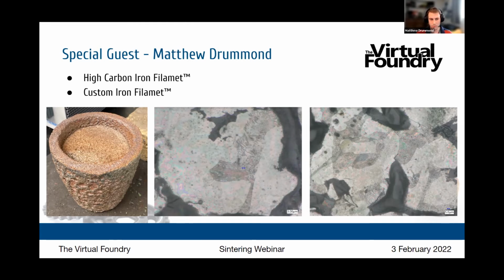I noticed with the crucible before on my sintering process, that actually one side of the crucible had not all the carbon eaten away, and one side was like that beige you see there. And that's because part of the crucible was right under the coil. So one side of the crucible is getting very hot just right underneath the coil, and the other side of the crucible is a lot less because there's no coil there and the carbon isn't being eaten as much. So it is something you've got to look at, and I think thermocouples within the crucible itself are a very good method to see what's going on within the crucible.